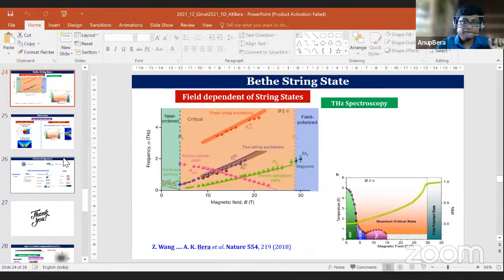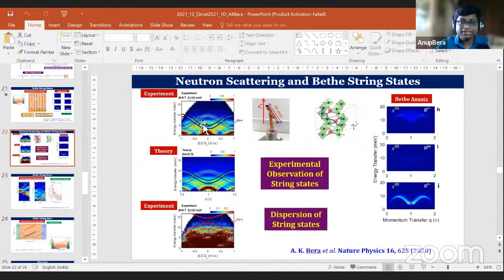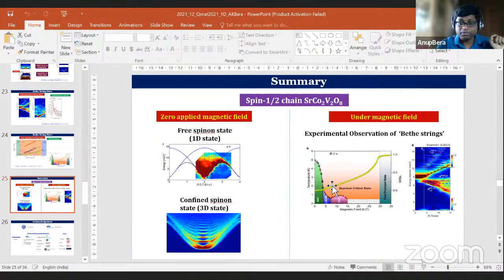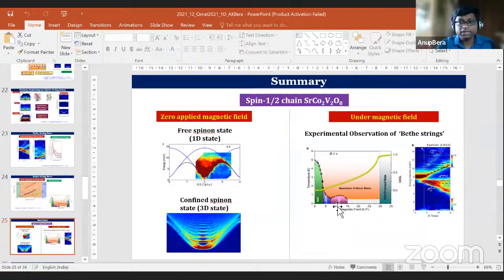Yes, I can show you, because the results I have shown here are basically measured at 50 millikelvin, even within this ordered state. But still we see this kind of quantum behavior, there is no ordering, because these are partial orderings of the spins, and they don't affect the high energy excitation or high energy physics of this compound. They only change something at very low energies and they stabilize this state. There is a very weak thermal fluctuation effect in this. But basically these are quantum effects, because we observe this state when we apply magnetic field. So it is totally driven by the magnetic field, not by the thermal energy.